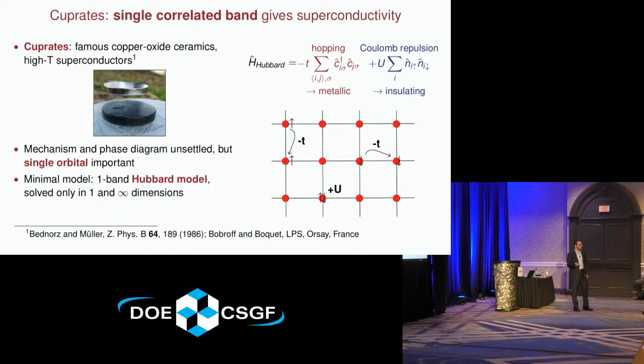The minimal model for this physics is called the one-band Hubbard model. It's one band just because we have that one d orbital. And the Hubbard model is this famous model Hamiltonian. I can describe it pictorially here. There are basically two terms. One's called a hopping term. This is just a lattice, and electrons can hop from site to site, and that's favorable with energy minus t. But if I have two electrons on the same site, they're going to repel each other electrostatically, and you pay a Coulomb repulsion cost of plus U. So basically, this hopping term leads to delocalized electrons and metallic behavior. But if we crank up U enough, this tends to localize the electrons, and one gets insulating behavior.